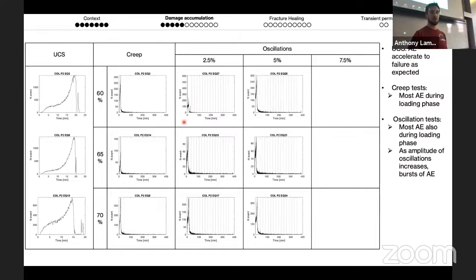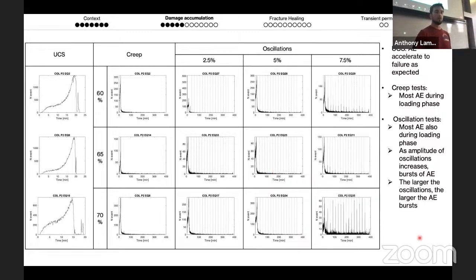But as we start increasing the amplitude, and that might be a bit small to see here, but the next one is quite striking, you see that as these oscillations are being generated, we get a small burst in acoustic emission. That's a lot more striking for the large amplitudes. You can see that these dashed lines are each of the oscillations. And every time we have one of these oscillation events, we have a burst of AE generated with it. So that suggests that there is micro cracking associated with these oscillations.